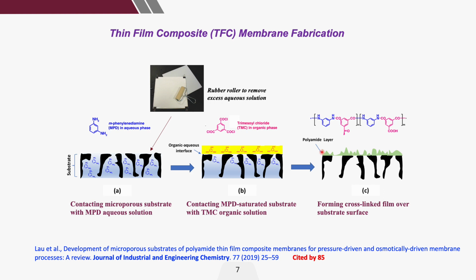And what I want to show you here is between step 1 and step 2, you need to use a rubber roller to completely remove the excess aqueous solution from the membrane substrate surface before you can introduce the second monomer. If you don't do that, you cannot produce a perfect polyamide layer.